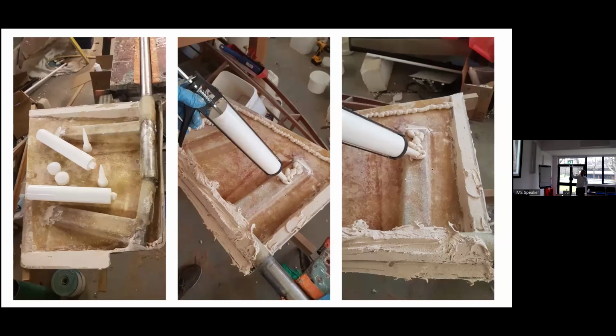I checked the stock to see if it was sound, and in my eyes, it didn't have any significant corrosion around it. So I decided to rebuild the rudder as it was. But it's a good indication of how these are built, where probably the moulding is set up horizontally on the bench. The stock is dry fitted to that horizontally, probably in a jig on this boat because it's a production boat. It's over laminated on one side. The two sides are probably put together with polyester bonding paste and then filled with polyurethane expanding foam.